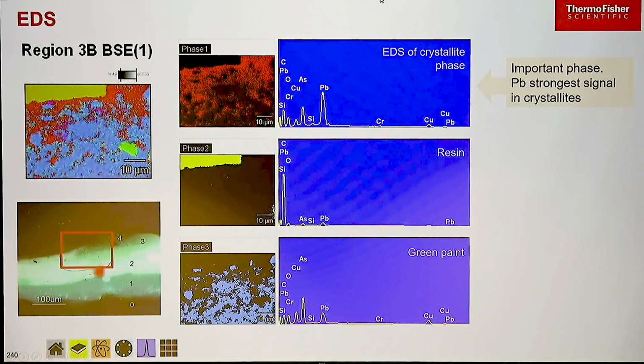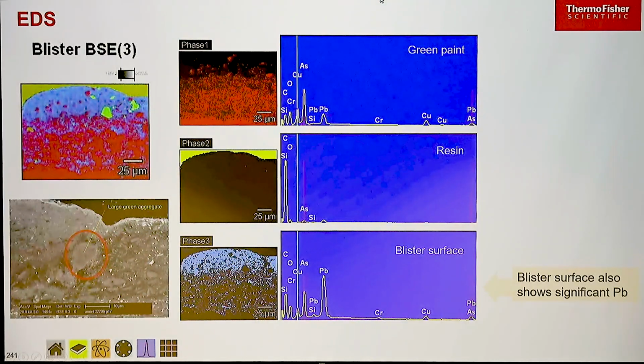Then the green paint down here has a lot of chromium and arsenic and copper in it. The lead typically comes from the white paint, something called Dutch stack white. It's principally lead carbonate, and traditionally it was made by taking pieces of lead, putting them into containers and then leaving them surrounded by horse manure, allowing a chemical reaction to occur on the surface from the gas coming off the horse manure. Very pleasant.